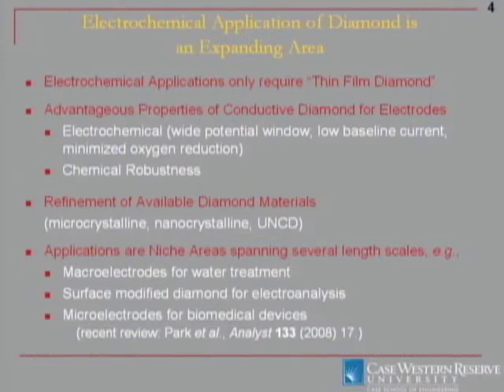There are several advantageous properties which I will come back to over the course of the talk, those being the wide potential window, a low baseline current, and minimized oxygen reduction, which is definitely very important in tissue applications because of the prevalence of oxygen in the tissue. And then last but not least, at least for the area of chronic implants, is the idea that diamond is chemically robust. Another reason that the use of diamond for electrochemistry is expanding is there are several different types of diamond materials now available. We originally started out making microcrystalline. There's also a couple variations on nanocrystalline diamond. This last one, ultra nanocrystalline diamond, involves a different type of gas environment. Instead of hydrogen, they use an argon-based plasma system to make the nanocrystalline films.